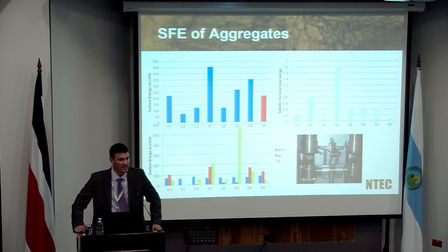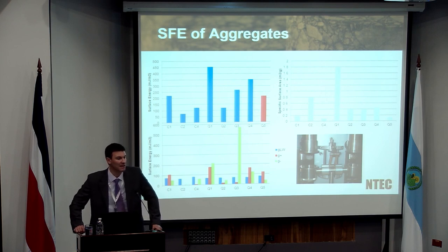The other thing to notice is that whereas bitumen tended to be, in the majority, a non-polar material, in other words, its main component was the non-polar part of those three components or parts of surface energy for bitumen, for an aggregate, each of those components is dominant. And so you will see large variation in terms of the acid component for some aggregates, large variation in terms of the basic components. And this becomes important when we start to look at how we would use thermodynamics to calculate your adhesion between bitumen and stone.